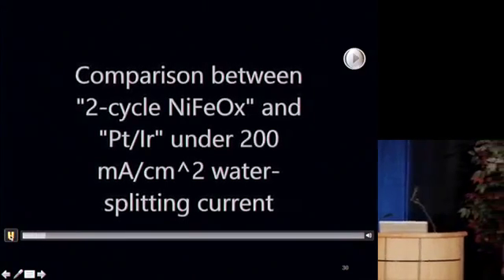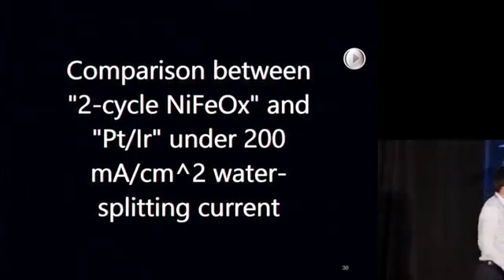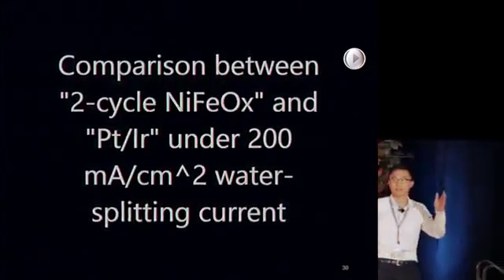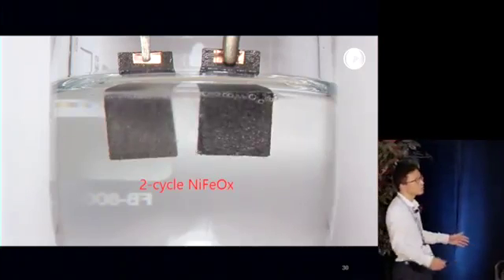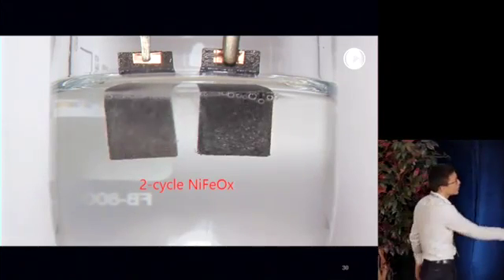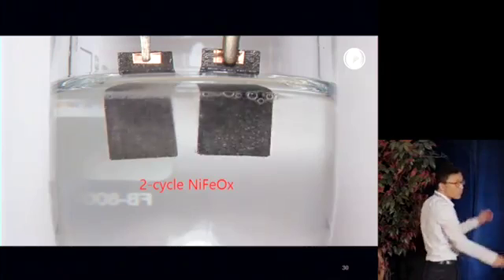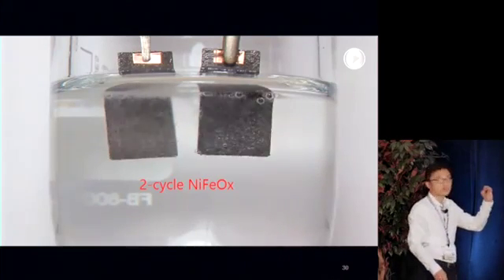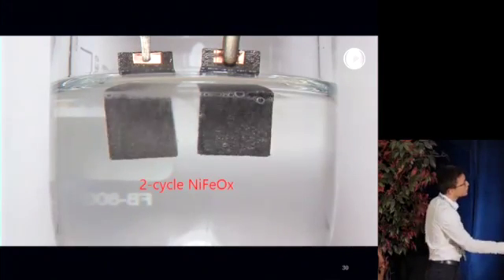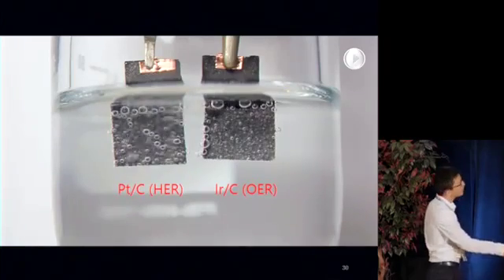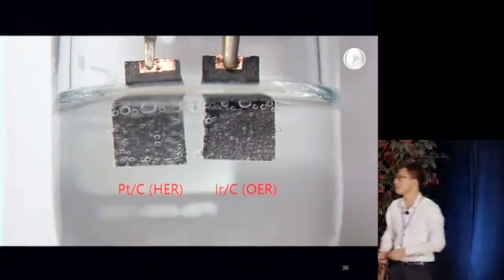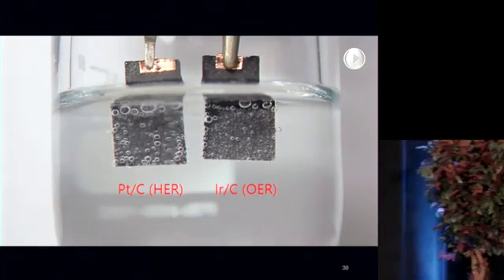So let me show you a video that compares my catalyst with the iridium and platinum. I drive both systems at 200 milliamp, which is a very high current density. You can see my bifunctional catalyst has very tiny bubbles coming out from the electrode. But if you convert to the platinum and iridium, you can see a lot of big bubbles covering the surface, blocking a lot of active sites.